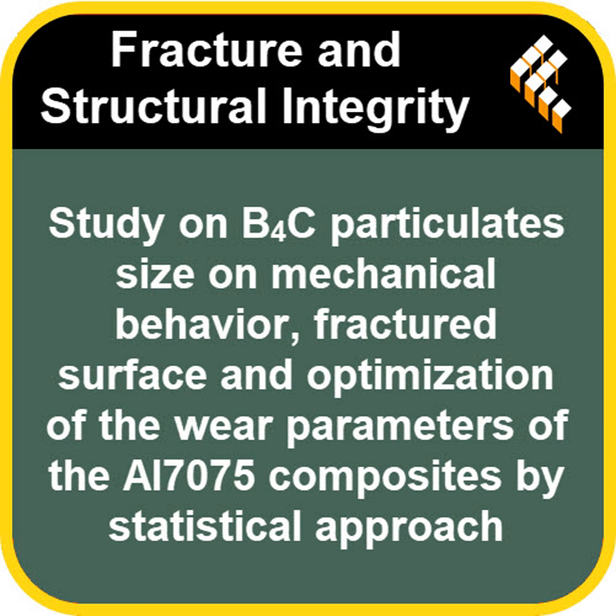Right, consistency is key. Okay, beyond the big performance numbers, I'm always fascinated by what's happening down at the microscopic level. When they looked inside these materials, what did the microstructures show? How were the particles actually behaving? Well, first off, the B4C particles, whether they were micro or nano, did significantly enhance stiffness, mechanical properties, and wear resistance. And that's because they create these strong bonds within the aluminum matrix, which helps transfer load effectively.